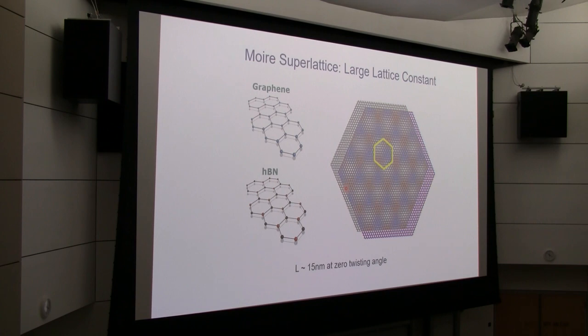If you play with 2D material, very soon people realize there's an interesting phenomenon known as Moire superlattice. So the idea is if you stack two layered materials together, depending on the atomic registration between them, in this case graphene and boron nitride, they all have hexagonal lattice. And when you put them together, because their lattice is a little bit different, the registry between the atoms changes over distance. And that change gives rise to a longer period lattice. And this is known as Moire superlattice.